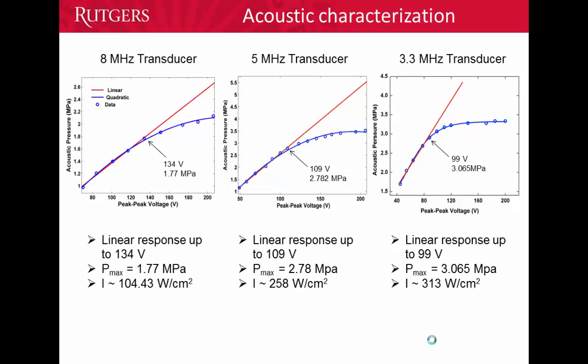Then the acoustic characterizations were done: the acoustic pressure versus peak-to-peak voltage. You can see that the 8 megahertz transducer shows a linear response up to 134 volts with a maximum acoustic pressure of 1.77 megapascal and intensity of 104 watt per square centimeter. The 5 megahertz transducer shows linearity up to 109 volts with a maximum acoustic pressure of 2.7 and intensity of 258 watt per square centimeter. And the 3.3 megahertz transducer shows nonlinearity after 99 volts, with a maximum acoustic pressure of 3 and intensity of 313.